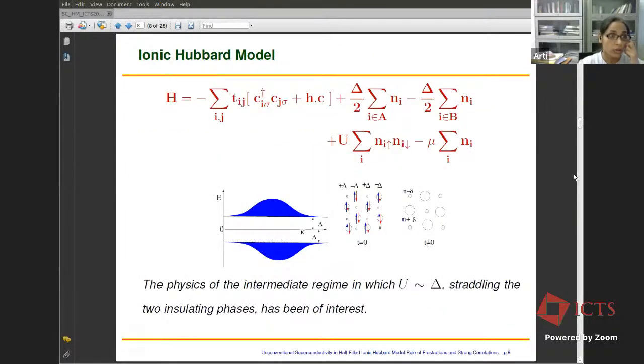So the starting point for us is a very simple variant of the Hubbard model, which is known as the ionic Hubbard model. The only difference compared to the Hubbard model is that we have a staggered potential. This model is basically defined on a bipartite lattice with two sublattices A and B, and then you have a staggered potential on those sublattices, such that sublattice A always prefers to have doublons and sublattice B always prefers to have holes.